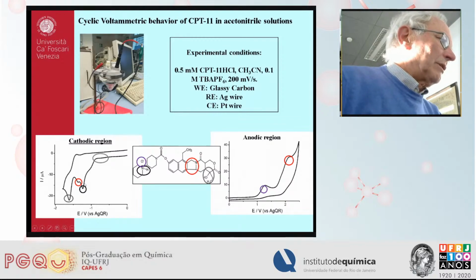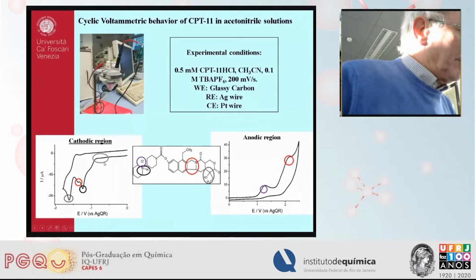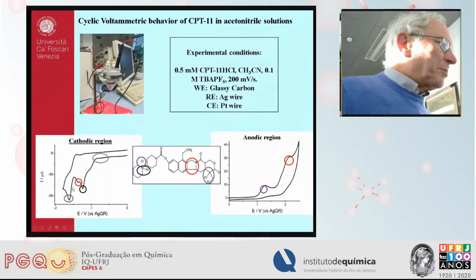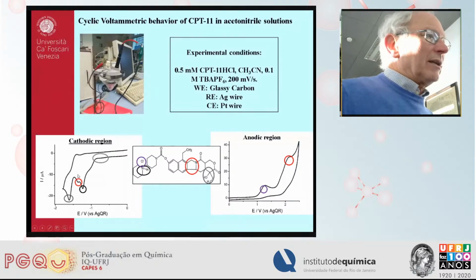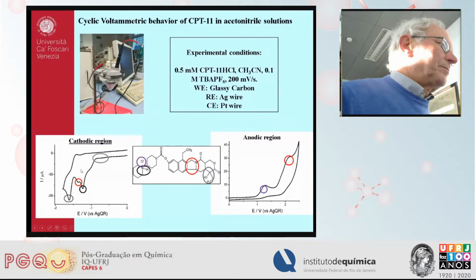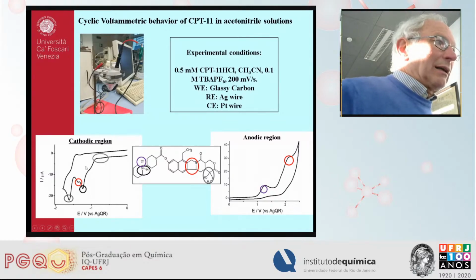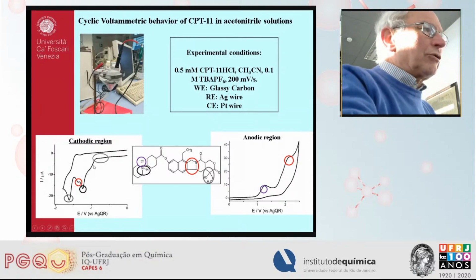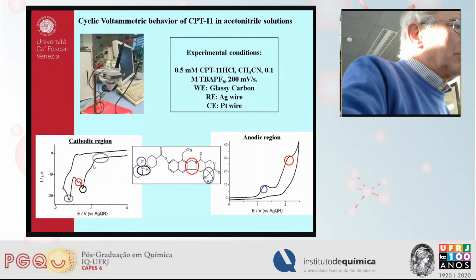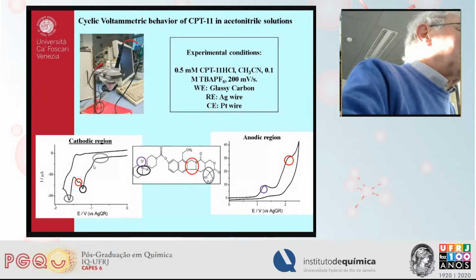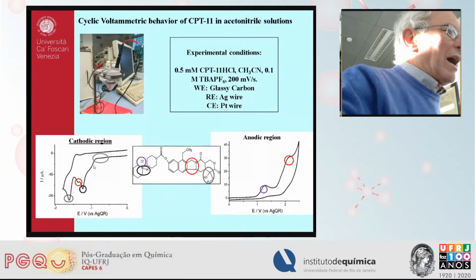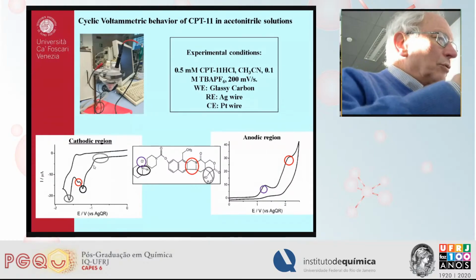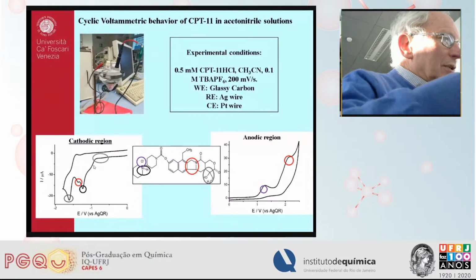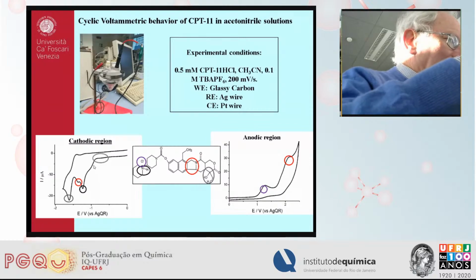In the negative region, there are several peaks which could, in principle, be exploited for detection of CPT11. But as I'll show you in the next slide, most of these peaks are also provided by the metabolites of CPT11. Moreover, for practical analysis, the cathodic region, from an electrochemical point of view, typically is not a good choice, because there are interferences also due to reduction of oxygen. Otherwise, we have to purge the solution with nitrogen or other inert gas.